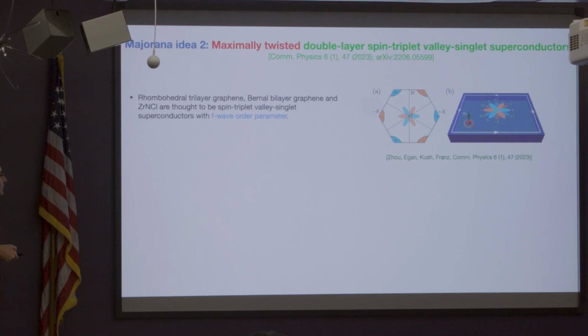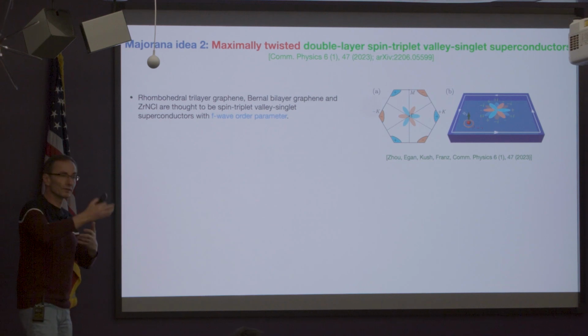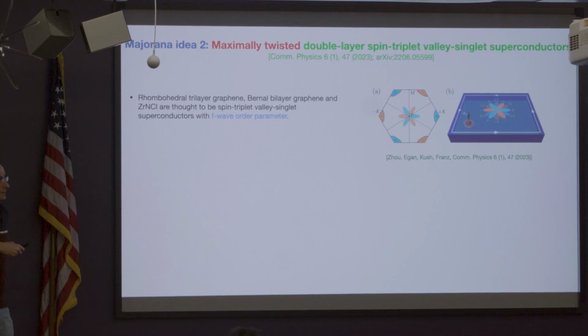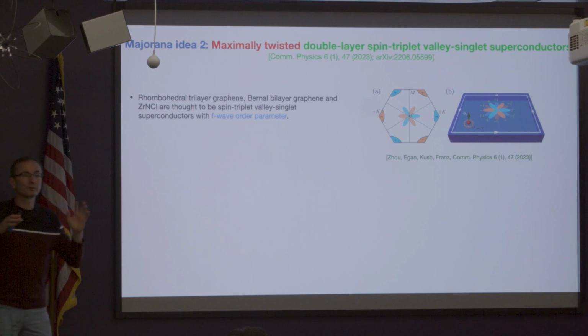And I'm not going to go there, but in some part of this phase diagram that Jane was showing us as a function of charge density and displacement field, their normal state looks like this. And importantly, these pockets here are spin polarized. So through interactions, the system just chose to fill only, say, spin up states, and they form this kind of metallic normal state. And then at low temperatures, this goes superconducting, right?